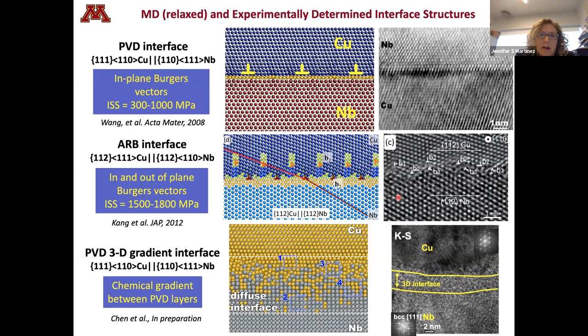So in the ARB, your dislocations are so even or semi-even in length and depth. Why do they form that way? Ah, so that's a good question too. So it all depends on what the low energy state is of atomic rearrangements to be able to relieve the structural mismatch between the copper and the niobium, which is also tied to its elastic modulus, right? And so you could rearrange these in one of myriad ways, but when we think about the disregistry in atoms between what has to happen in copper and what has to happen in niobium, there's going to be certain configurations of those dislocations because their elastic strain fields interact with one another.